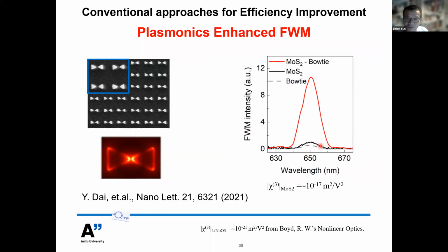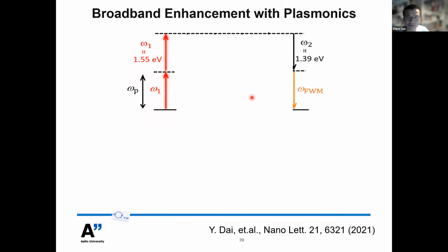The 4-wave mixing signal is very weak, but when you combine this bow tie antenna structure with the MoS2 devices, you will get around 10 times enhancement. We also demonstrated broadband enhancement with plasmonics. People may think this is impossible with a plasmonic structure, because traditionally people always think the plasmonic resonance is very sharp. It's not possible to get broadband enhancement with plasmonics. So here we used a very smart strategy.